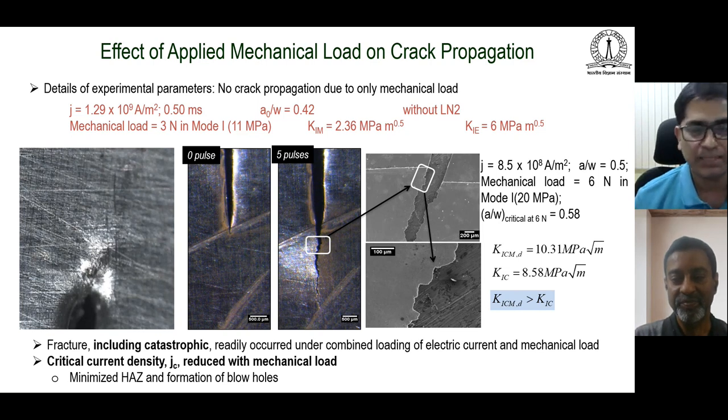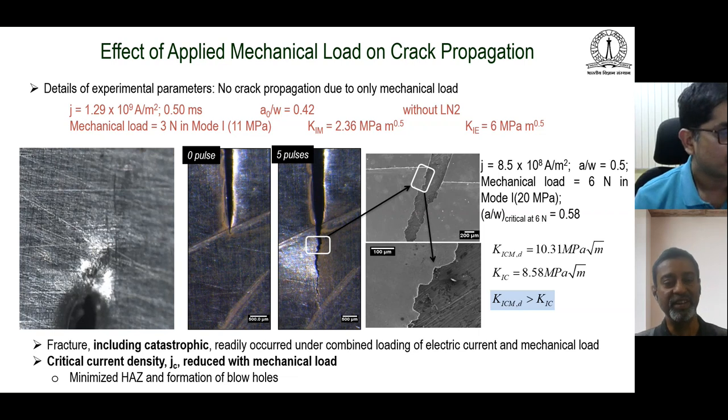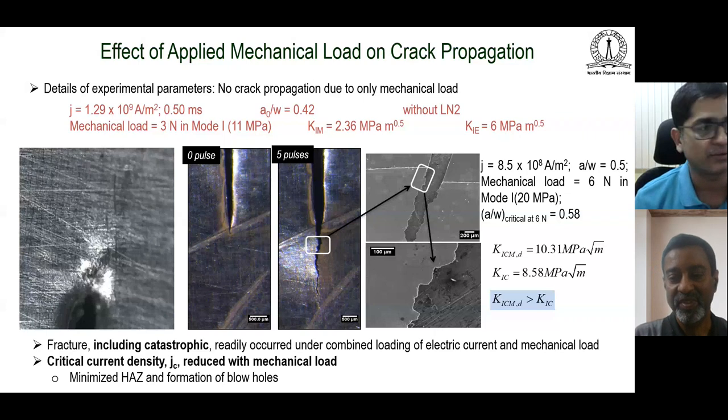But in principle, it should be easier to do on a thicker film in some sense, because the temperature can easily rise to a higher value, and that's because you have stainless steel whose specific resistivity is high. Very high, yes. We could not do these experiments yet on aluminum, because there's no temperature gradient, and the compressive stress that is built is very little. So we just get the fracture.